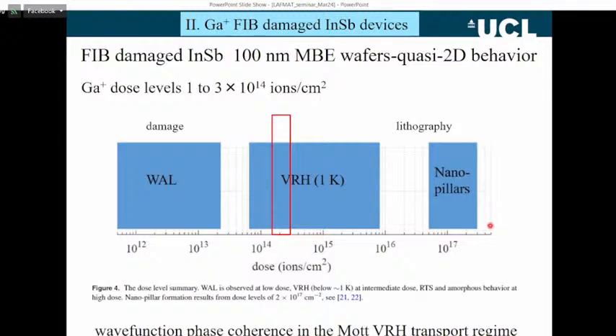So we've got this system now, this indium antimonide. It's not suspended. We've still got an anchor to the substrate, but we can introduce damage in a very, very controllable way. So again, this is the same data. This is dose level here, ions per square centimeter. So it's a dose of gallium ions. It's done in a FIB system. It's a nice system for creating disorder.